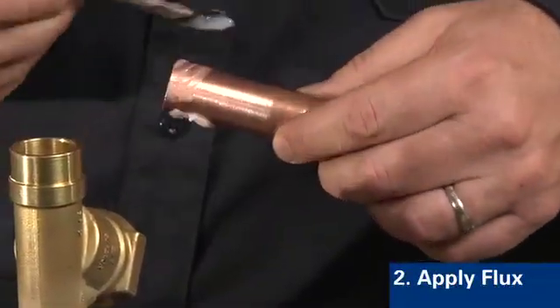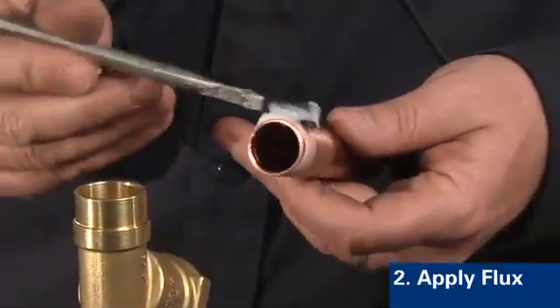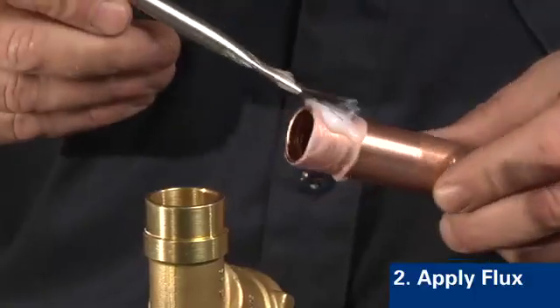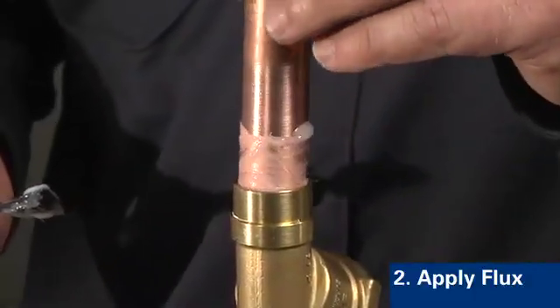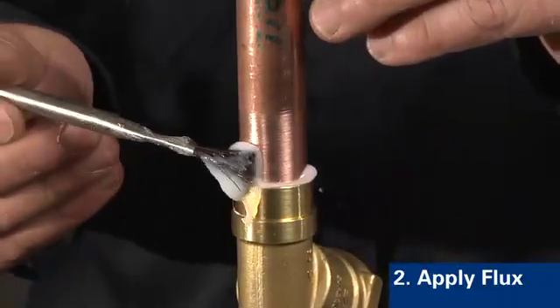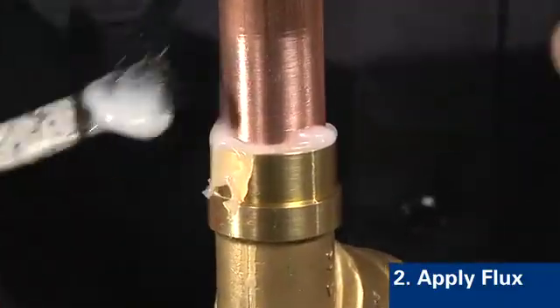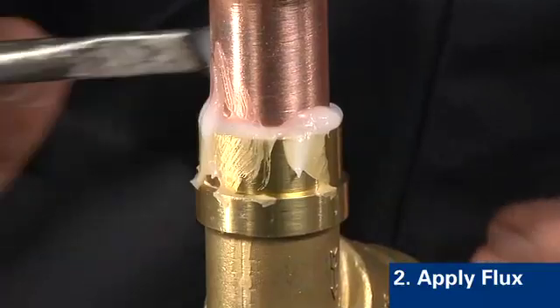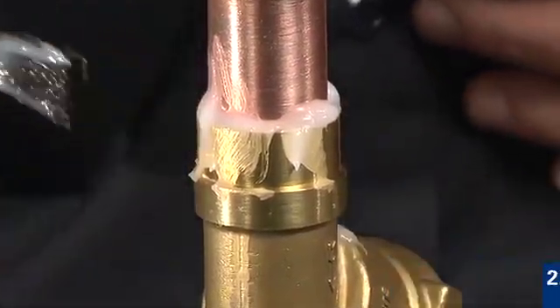The next step is to apply flux to the assembly. When applying the flux, a uniform brushed-on coating is all you will need. Overfluxing or underfluxing of joints may lead to problems in the process, such as increased porosity in the braze joint or difficulty removing flux residue.